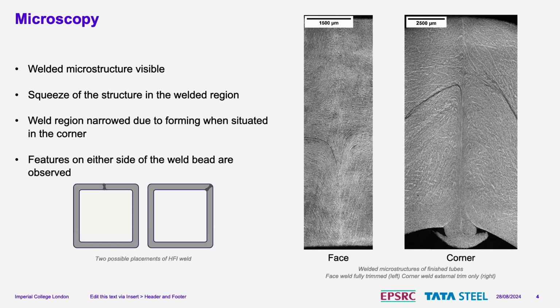We get this banded microstructure, which is quite typical of a hot rolled steel. And you can see in the welded region, we've had this squeeze, and you can see how it's all moved in that direction. And when it's in the corner, you get a much thinner weld section. One important thing to note is that here you get a couple of features on either side of the weld bead. And this is proposed to be, as it's pushed into the corner, we get some folding of the material.